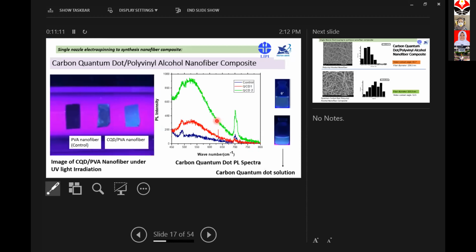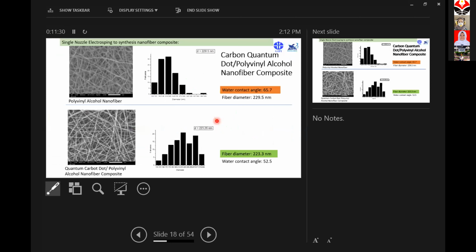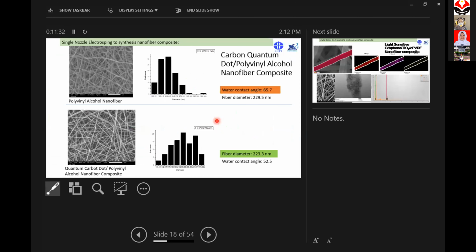First, we synthesize carbon quantum dots by microwave technique, and then we make a PVA, polyvinyl alcohol, and quantum carbon dot solution, and then we do the electrospinning process. Here you can see the morphology of the polyvinyl alcohol nanofiber. You can see here it's a good polymer solution, and we can get very smooth and homogeneous nanofiber with diameter around 229 nanometers.